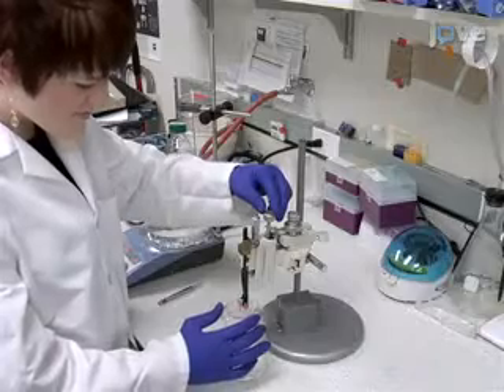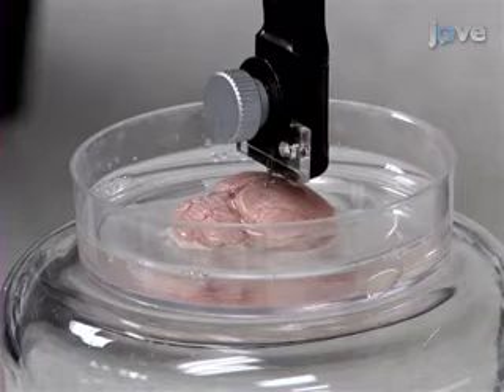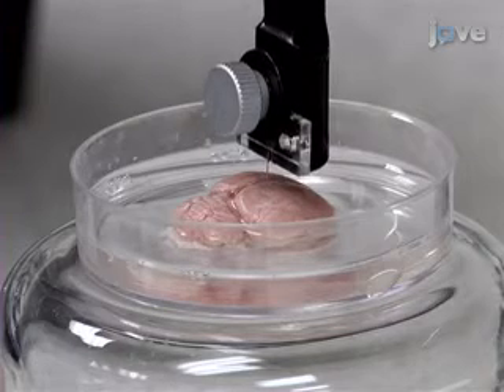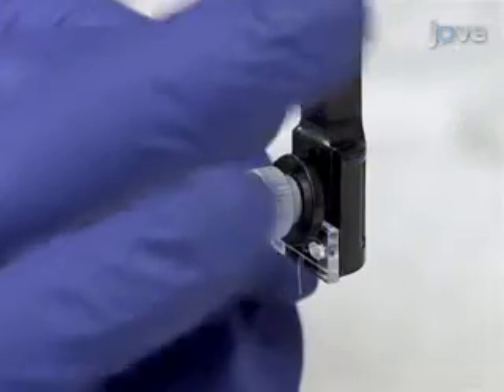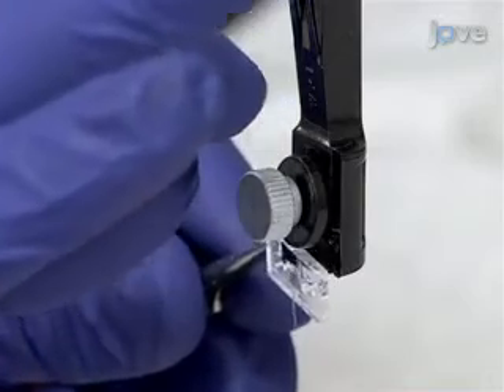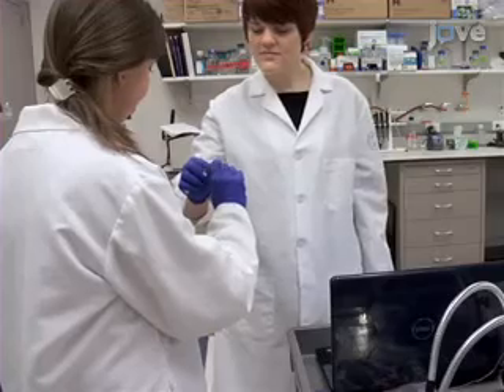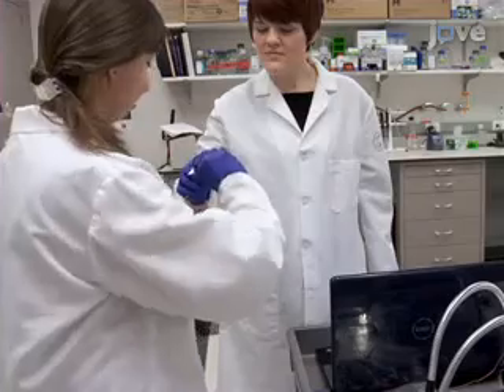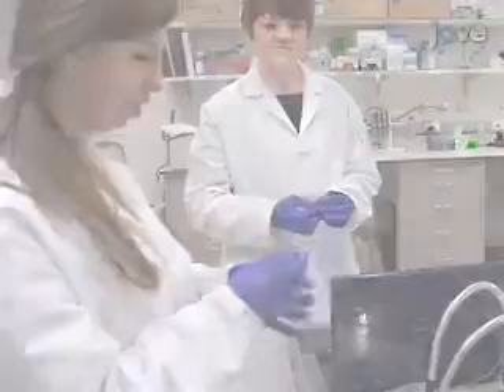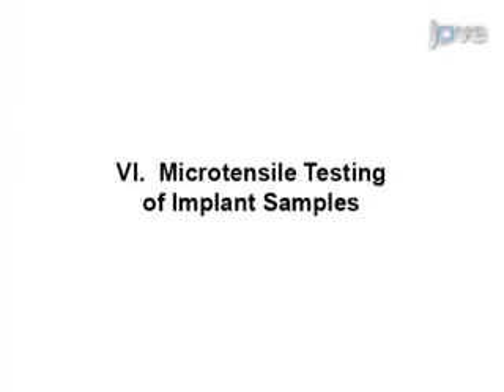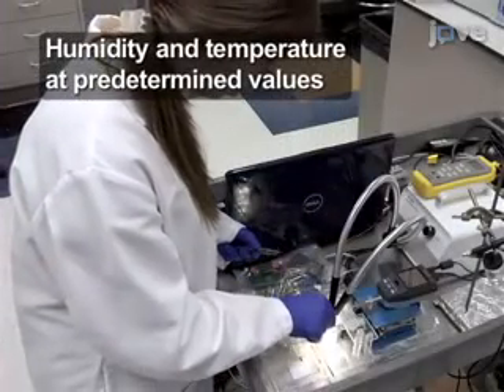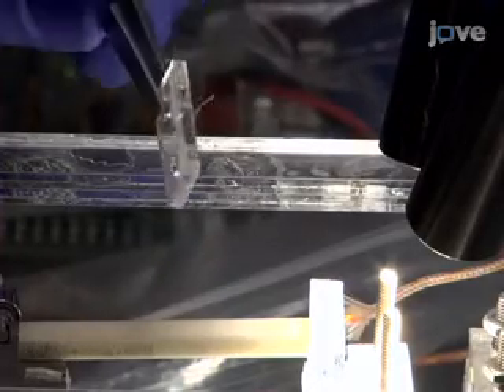At the end of the specified implant time, raise the probe out of the cortex using the micromanipulator hand controls. Immediately and carefully remove the sample from the micromanipulator clamp and take it to the microtensile tester to begin testing within 2 minutes. Immediately after explantation, load the sample between the two sets of microtensile tester clamps.